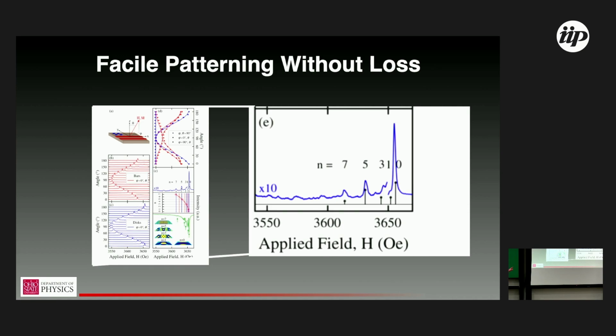And we can compare that to the blue data here, and it's easier to see in the full figure, but out to the seventh order spin wave, there's quantitative agreement. So there are no adjustable parameters in the mu-max fit to get these resonances to line up. They just line up. And then just to remind everyone, these black dots here represent an analytic calculation of a cylinder with the appropriate dimensions, and that also does quite well.